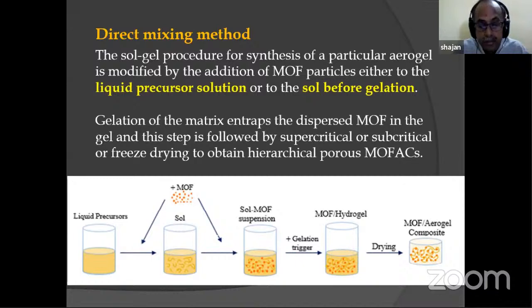Second one is the compatibility of the solvent that you are using. Suppose in that solvent, the MOF dissolves, it's easily soluble in the solvent that you have chosen for the preparation of the aerogel. So the aerogel will be obtained, but the MOF is easily soluble in that solvent. Then the MOF structure is totally collapsed. It is dissolved into the solution. So compatibility is very, very important, that the MOF should be stable in the solvent you have taken.